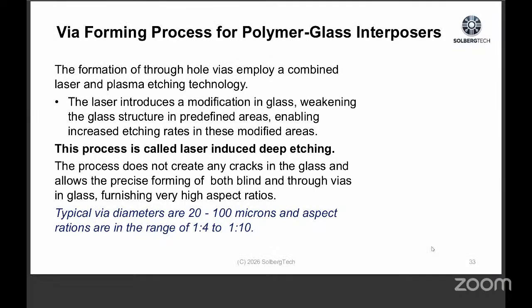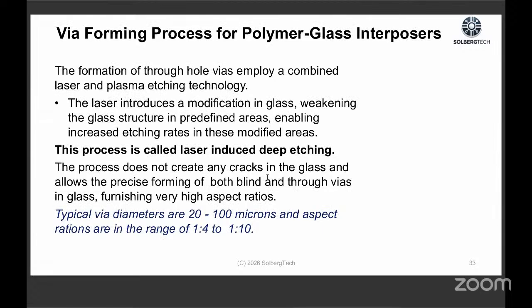So the forming process for polymer glass is the laser introduces a kind of modification in the glass, weakening the glass at predefined areas, and that enables increased etching rates. The process is called laser-induced deep etching. It does not create any cracks in the glass and allows precise forming of both blind and through vias, furnishing very high aspect ratios. The typical diameters are 20 to 100 microns, aspect ratios in the range of 1:4 to 1:10. Next.